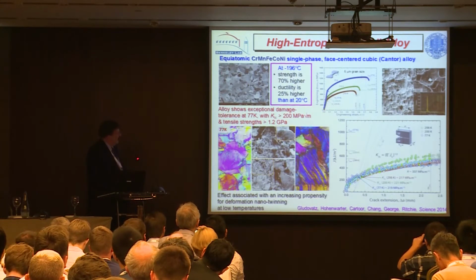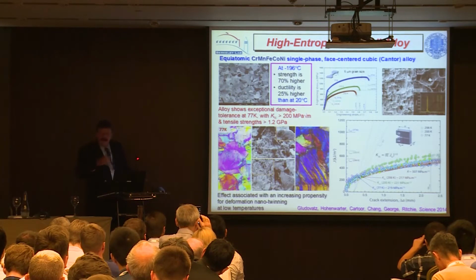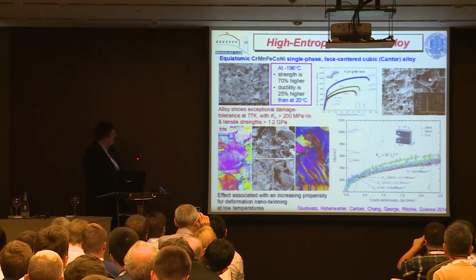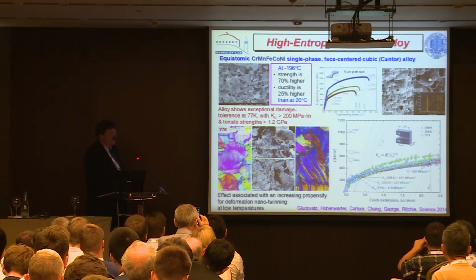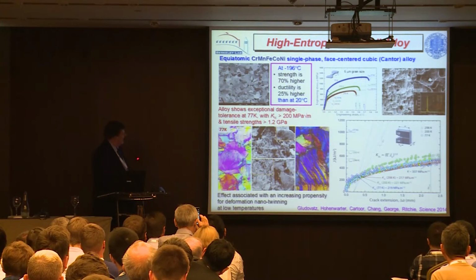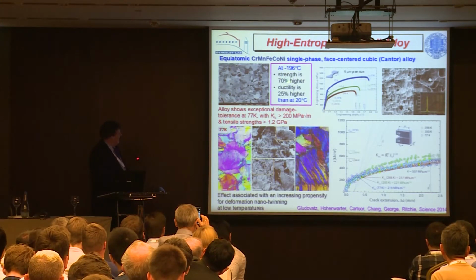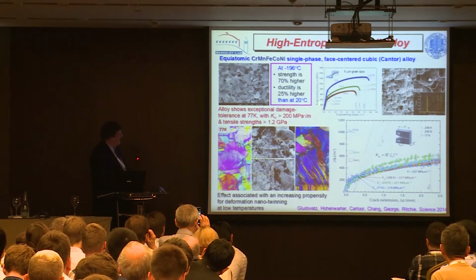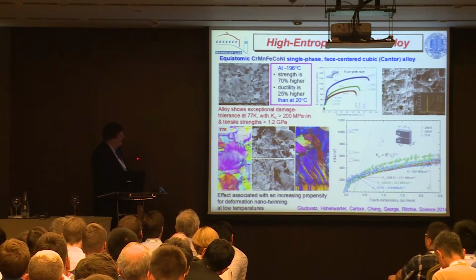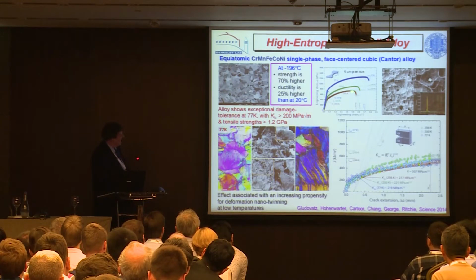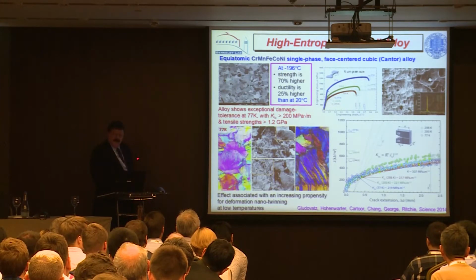A lot of work was done in China and in various places for 10 years or so, but then Easo George at Oak Ridge got involved and started to make very good material. We got access to this material, and this is quite well known now that this material, this Cantor alloy, has pretty good properties at room temperature. It has a strength of about 800 MPa and a ductility of the order of 50 or 60%.